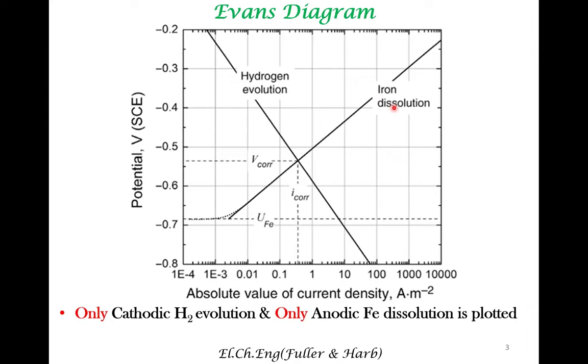That is, iron is getting corroded, and we present the data above the equilibrium electrochemical potential, referred to as UFE here. So as we go in the anodic region, as the anodic potential is increased, the iron dissolution increases. The equilibrium electrochemical potential for hydrogen evolution reaction is not shown here. But as you can see, as you go in the cathodic direction, the hydrogen evolution rate increases. So in the previous plots, corresponding to these two different reactions, we presented the overall current. Here only part of the current is being presented. Only the cathodic part of hydrogen evolution and the anodic part of iron dissolution is being shown.